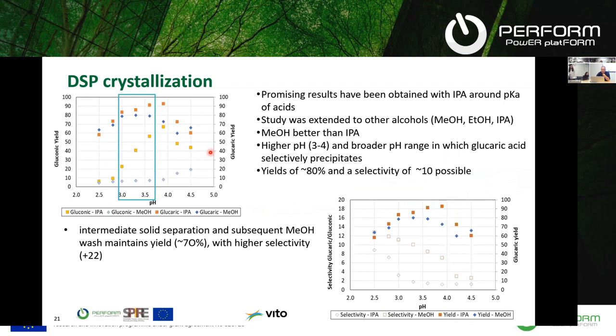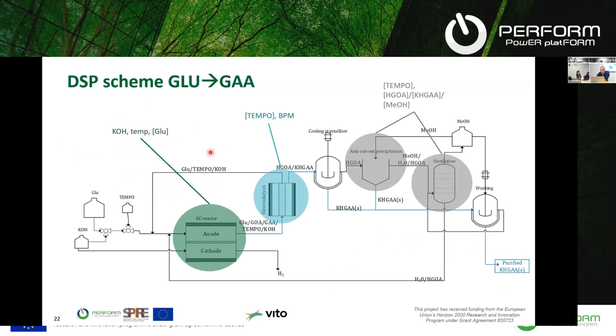And as you can see here, there were initial promising results with isopropanol, but when the study was extended to other alcohols, and especially with methanol, we were able to achieve very high yields of recovery for glucaric acid, 80%, and a selectivity of 10 just in a single crystallization step. The nice thing with methanol is that you can also use it subsequently to wash any precipitates that are formed and further increase the purity even with a factor of 22. So this provided a very solid DSP route, let's say, to separate and to purify the glucaric acid from the reaction mixture.